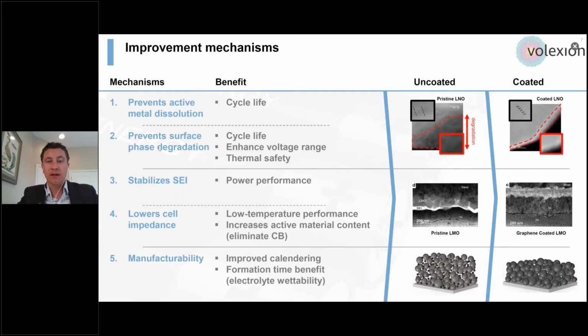In terms of how the technology works, there's 5 improvement mechanisms that we provide to and drivers of benefit that we provide to cathode material. One is we prevent the dissolution of active metal that then leave the cathode material, migrate to the anode, and accelerate aging. We prevent the surface phase degradation of the cathode material, so crystalline to rock salt transition, which is the picture that you see on the right-hand side. And we keep that boundary layer very well defined between the cathode material and the electrolyte over the life cycle. We also, in terms of power performance, we stabilize the solid electrolyte interface, and we lower the cell impedance thanks to the higher conductivity of the graphene.